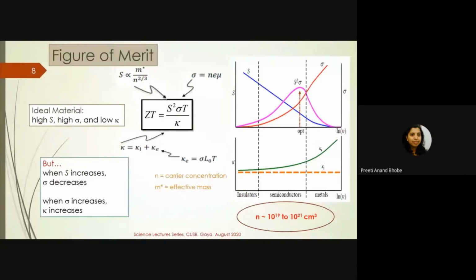So if this is the golden number in which you can get a good ZT, which are the materials that qualify in this region? These are the semiconducting materials. Semiconducting materials are known to have a charge concentration that lies between 10 raised to 19 and 10 raised to 21. Metals like copper and all are higher, 10 raised to 22 and higher. Insulators will have 10 raised to 14, 15, 16, much below 10 raised to 19. So the ideal number to get a good ZT lies in the region of 10 raised to 19 to 10 raised to 21. And so scientists started looking at materials that have this kind of concentration.